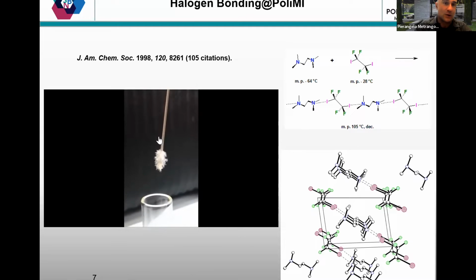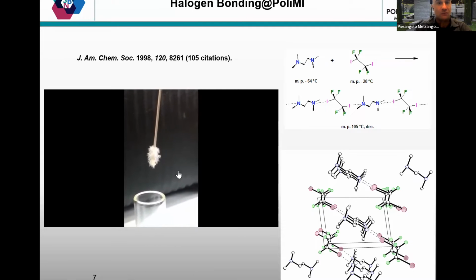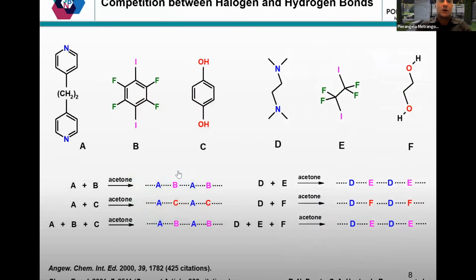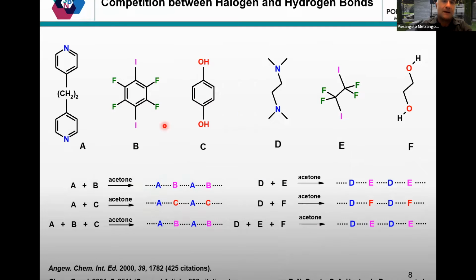And this is what we are using nowadays for teaching students what supramolecular chemistry and halogen bonding are, because it's a very, very easy and astonishing experiment. So later on, we wanted to compare the halogen bond with the most known hydrogen bond, and therefore we did some, I would say, simple crystallization, competing two halogen bonded species with one hydrogen bond donor, like hydroquinone, and we only obtained the halogen bonded co-crystalline solution, also in the aliphatic series.